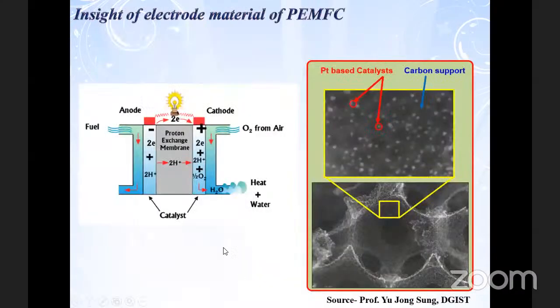Okay. So if you look at the catalyst layer here, you will see mostly carbon, highly porous carbon materials are used there, and the platinum small nanoparticles are deposited on that catalyst support. And this platinum works as an active material for the anode reaction, where the hydrogen is split into H plus and electrons, and carbon gives the support so that the maximum platinum can be deposited, and that can be used for this reaction.